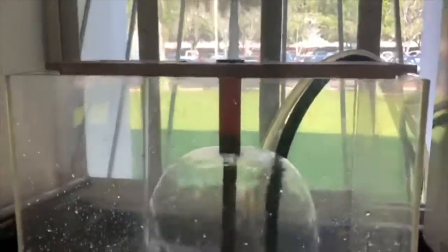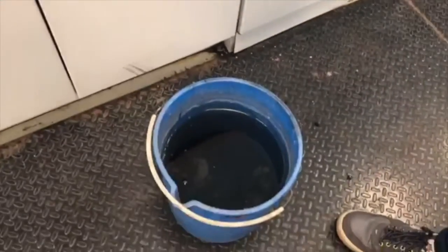And after that, we need to be really quick because this step needs to be done in less than 5 seconds, and it's to take out the piece from the oven and put it into the hole of the Jominy device. The water will be flowing and the Jominy specimen will be cooled down gradually. This will leave different hardnesses on the piece. We'll leave the sample in the Jominy device for 10 minutes, and then we put it in a bowl of water in order to cool down completely.